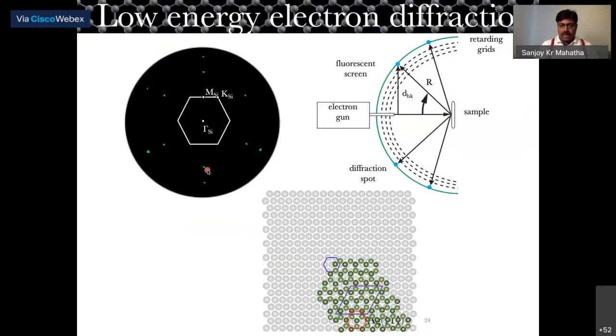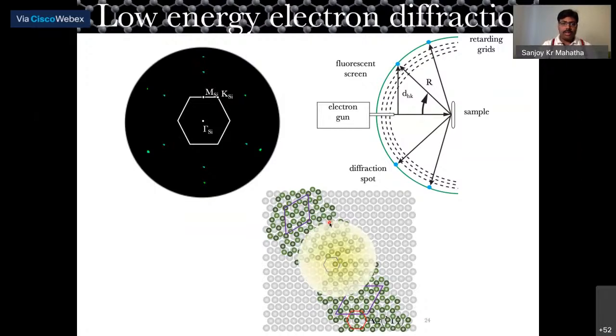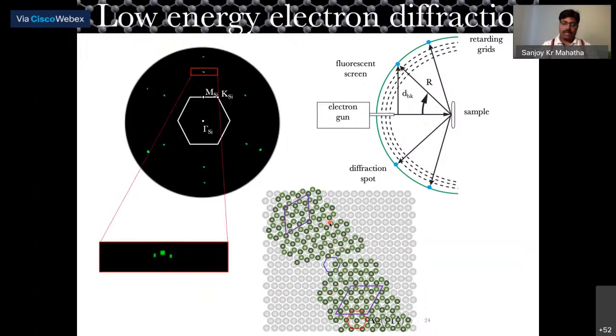And we can have a different structure of silicene on top of the surface, which is probably rotated by a few degrees. You can see it's the same structure, but rotated with respect to the silver 110 axis. And then if we shine the electron beam on both the structures, then you would see some extra spots in the low energy electron diffraction. So here you can see if you zoom in, there is one spot from silicene and there are 2 different spots coming from this structure, because this structure can be rotated clockwise or anti-clockwise, and there will be equal distribution of those two rotated domains. And this is what we would get.